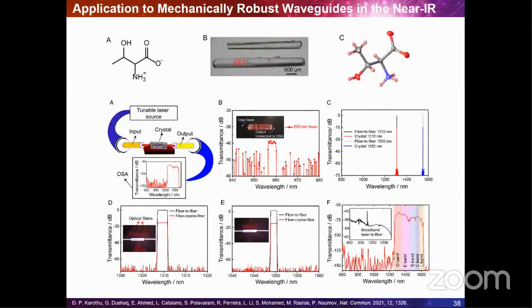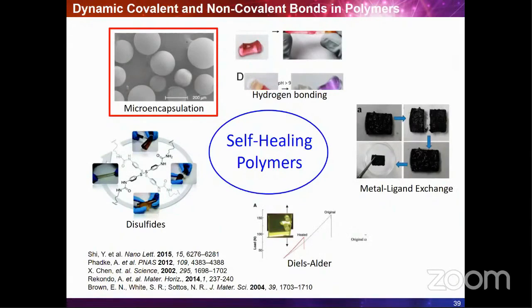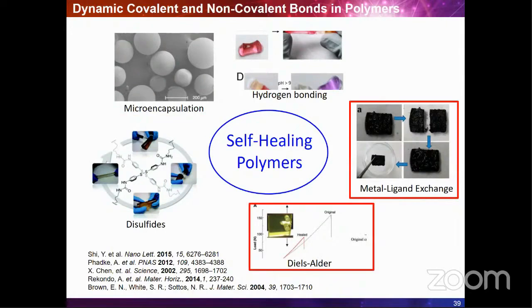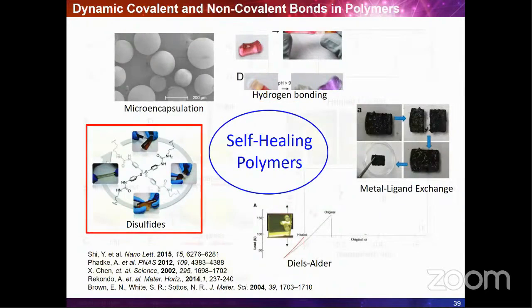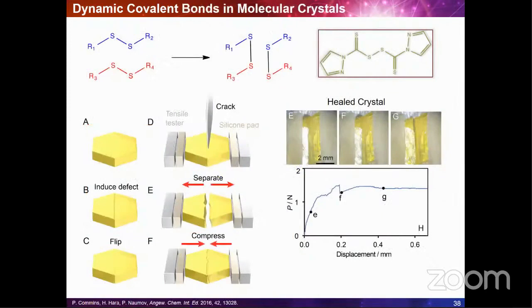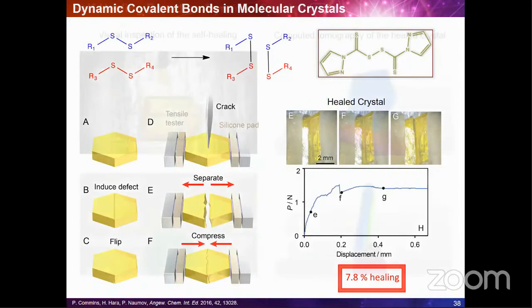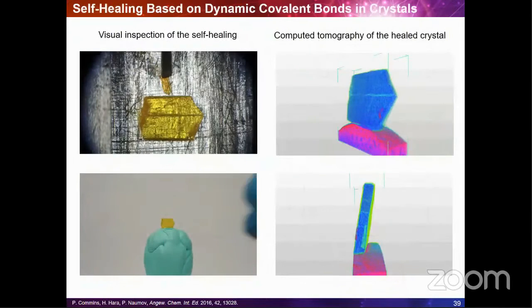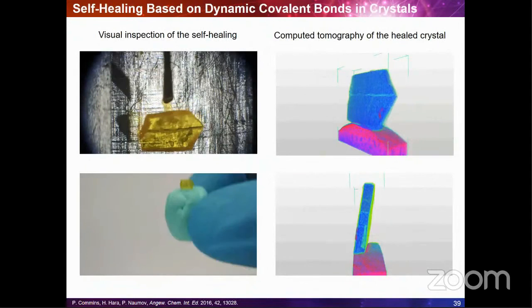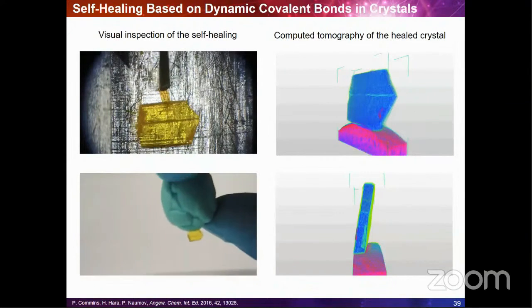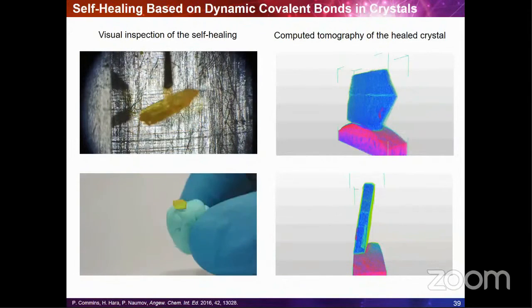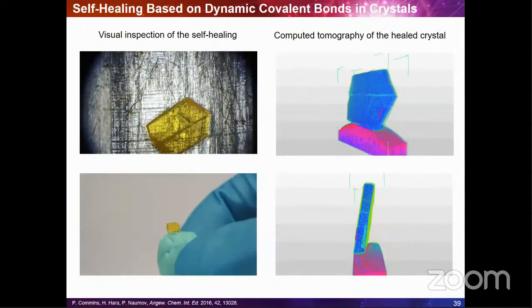So I'm going to just show you some of the self-healing polymers that we used as an inspiration to create self-healing crystals. And of course, we made the self-healing crystals based on disulfide shuffling. They are shown here. We achieved 7.8% self-healing in these disulfide-based crystals, but then by using other chemistry, we improved this efficiency. So here, for example, you can see self-healed crystals, which can be mechanically disturbed without losing the integrity.